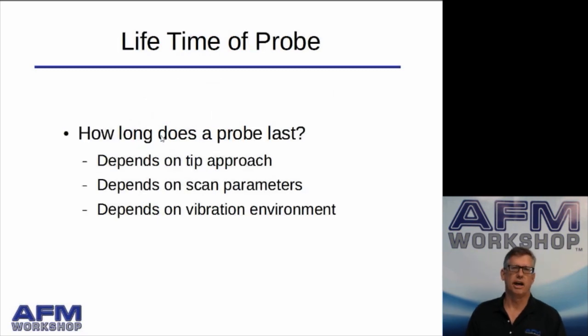One of the questions that comes up when people start to do atomic force microscopy is: what's the lifetime of a probe? How long does it last? The answer to this question is it depends. These are the things that it depends on. It depends on tip approach. When you're running your microscope, if you're able to do a proper tip approach and the probe comes down and very gently comes to the surface, the tip will be preserved. However, if you're not careful in doing the tip approach and maybe the instrument's not tuned up, it'll hit. And if it hits, it could break the probe.